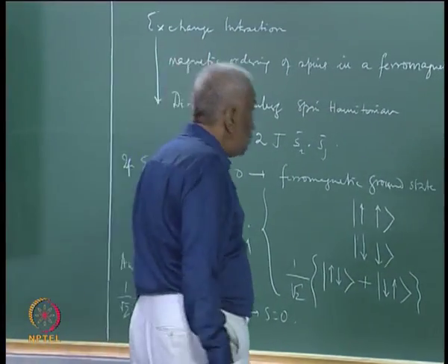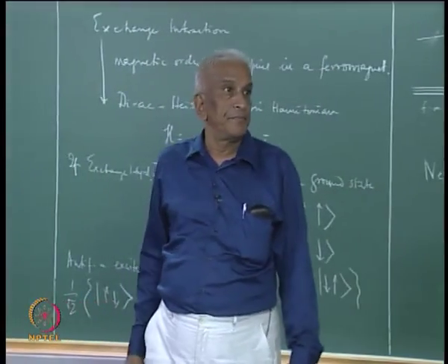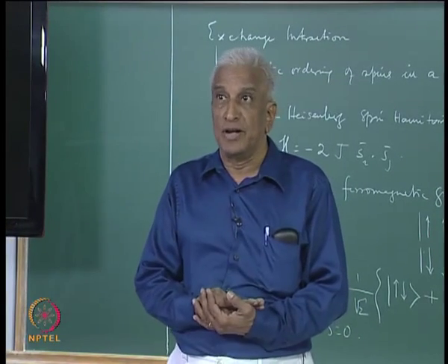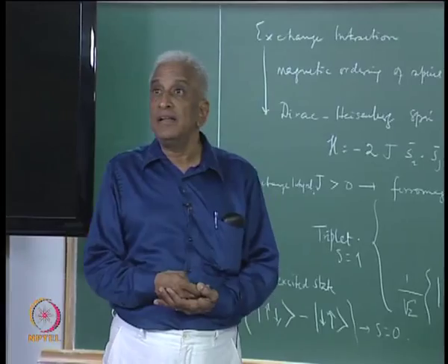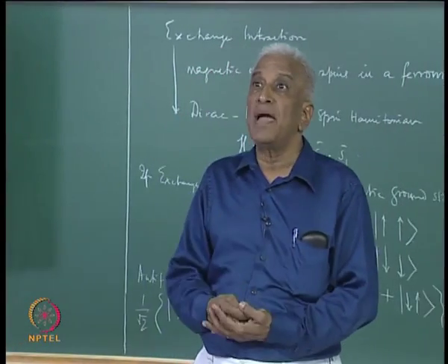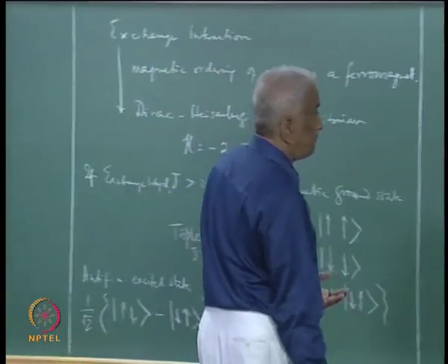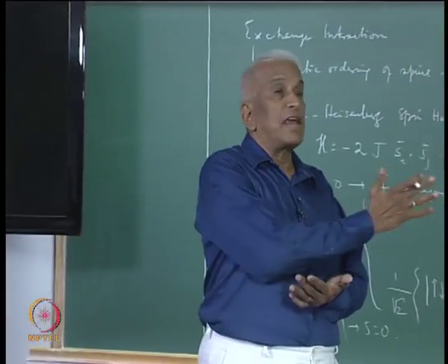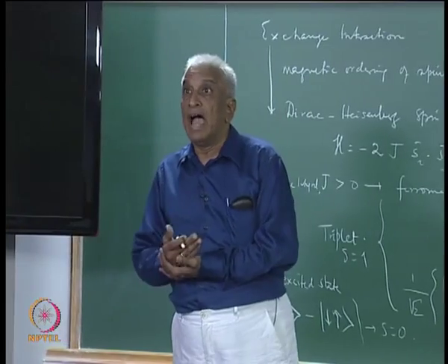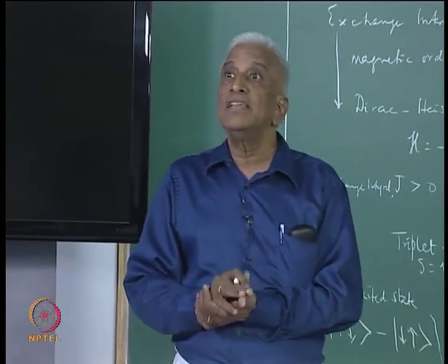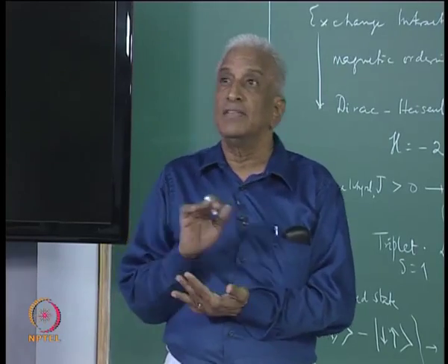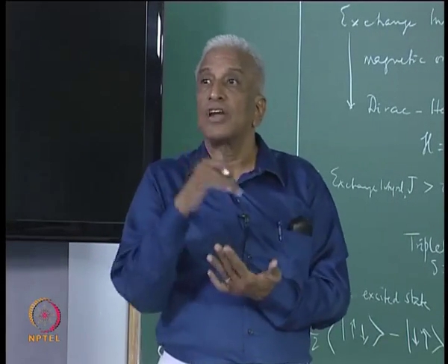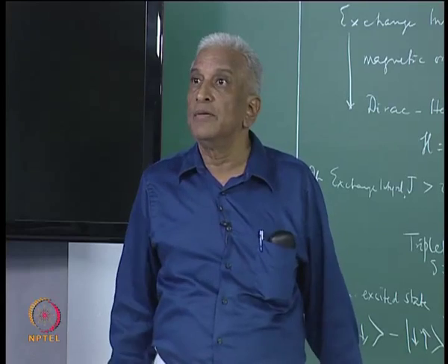This is because neutrons have a magnetic moment, even though they are electrically neutral particles. Because they have a magnetic moment, the neutrons can interact with the spin magnetic moments of the ordered spins in the crystal lattice. Therefore, because of this interaction, they can be diffracted just like X-rays get diffracted by atoms in the crystal lattice. Only thing is, the interaction here is magnetic, whereas in the case of conventional X-rays, the electromagnetic waves interact with the charge clouds of the electrons in the material.